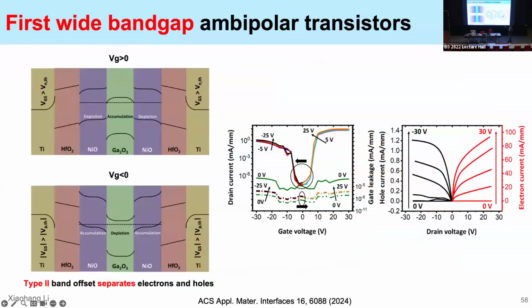So this is how it works, a little bit of physics. If you look at the right, when you have the gate voltage larger than 0, you have the move up of the Fermi level, which creates the accumulation of electrons in the gallium oxide, but then depletion of the nickel oxide. So when your VG is larger than 0, you only have the electron current. But when your VG is smaller than 0, you have the depletion in gallium oxide and then accumulation of holes in nickel oxide. So in this case, you output hole current. So by applying different bias, we can actually change whether the transistor is NMOS or PMOS.